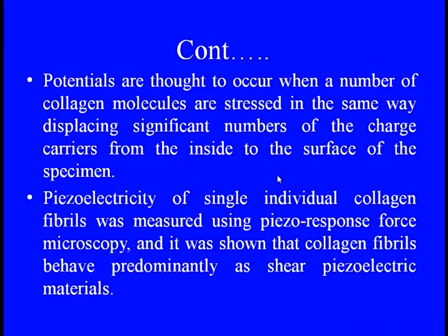Piezoelectricity of single individual collagen fibrils was measured using piezo-response force microscopy, and it was shown that collagen fibrils behave predominantly as shear piezoelectric materials. So this is a clear exhibition of the piezoelectric feature, where force is applied and electrical outputs follow according to the action.